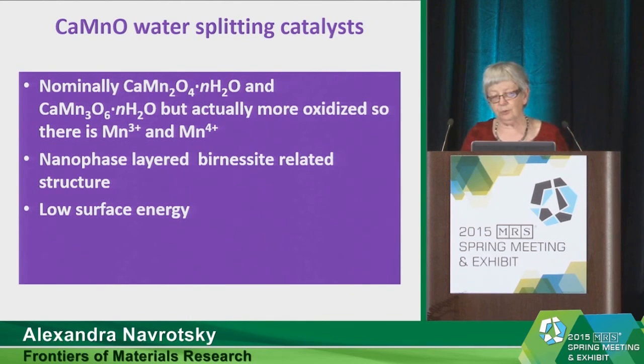Now let's imagine some sort of reaction in which one wants to transfer electrons and/or transfer ions through the interface. The interface, let's say, between the oxide and water. In order to have that sort of transfer, if the water on that interface or that surface is held really tightly, then it's difficult to move some other ion, a lithium in a lithium ion battery, manganese ion in and out of solution, etc., because it has to displace a tightly bound water. Therefore, one of the things that, in addition, makes these materials good catalysts is having relatively loosely bound water.